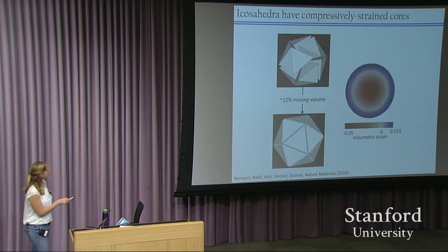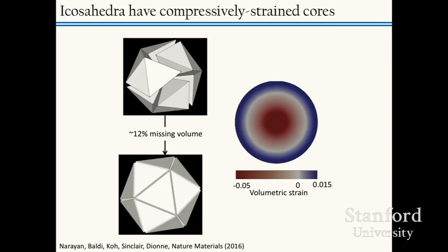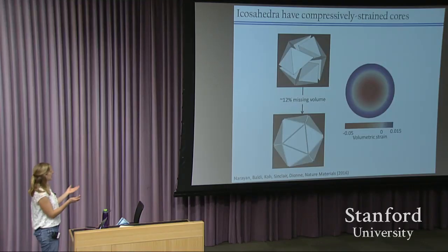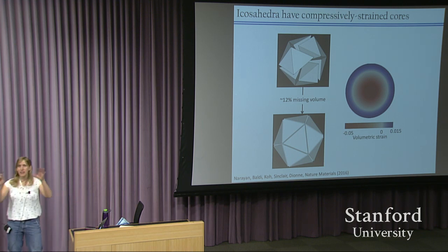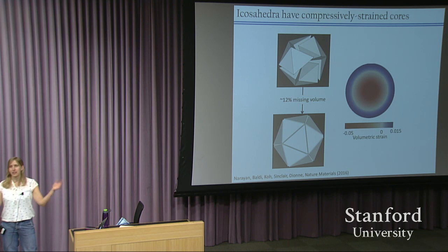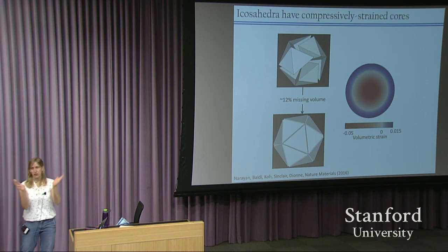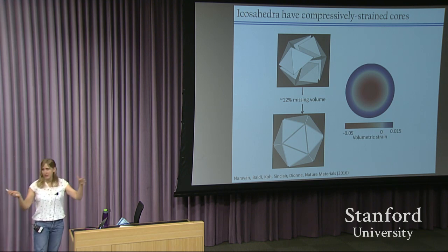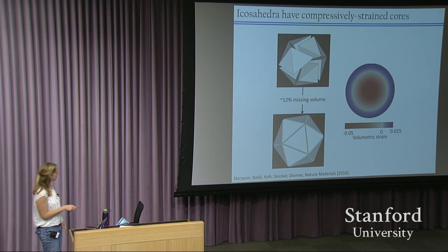So our hypothesis is that if you consider what an icosahedra is composed of, it has 20 tetrahedra that don't quite fit together perfectly. So if you want to colloidally synthesize one of these nanoparticles, it turns out that all these tetrahedra pack together, but they leave a strain gradient where the core is compressively strained and the outer part of the icosahedra is tensely strained. So the tetrahedra need to pull apart at the surfaces to make one solid nanoparticle.